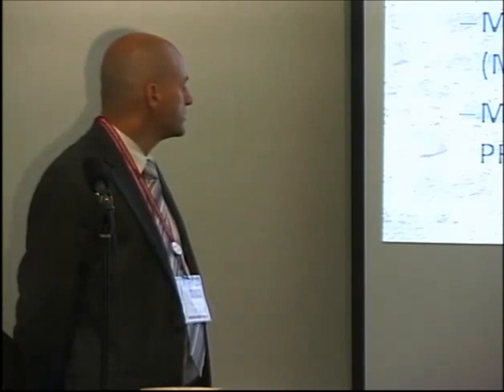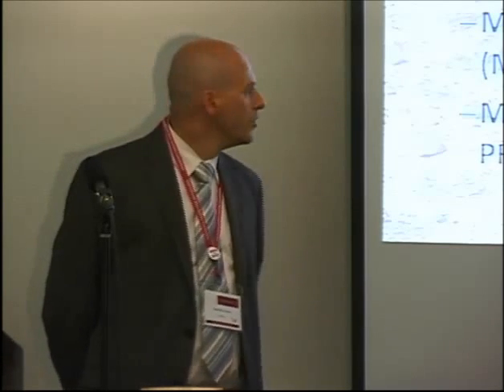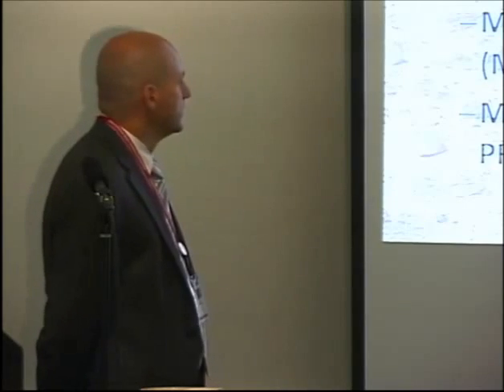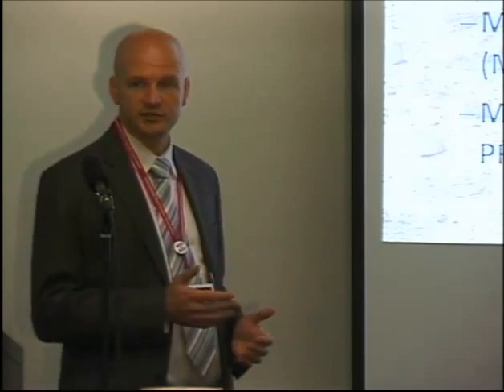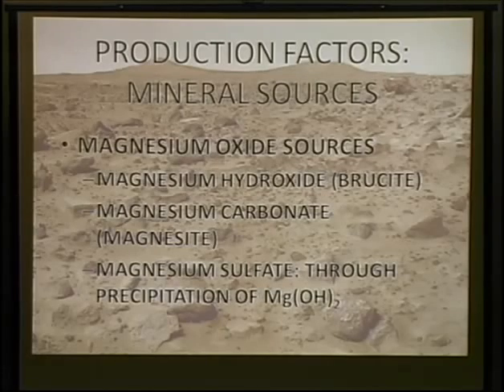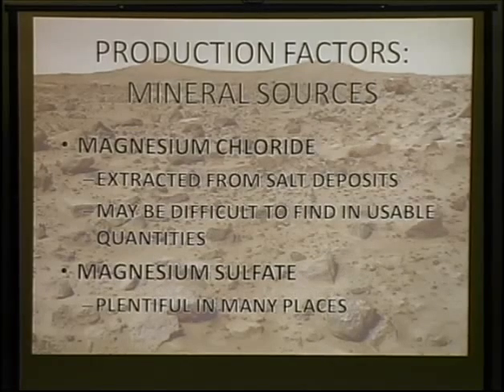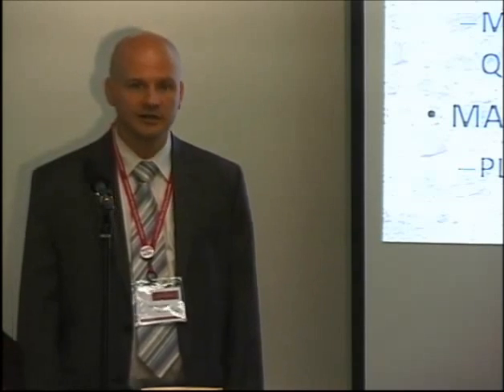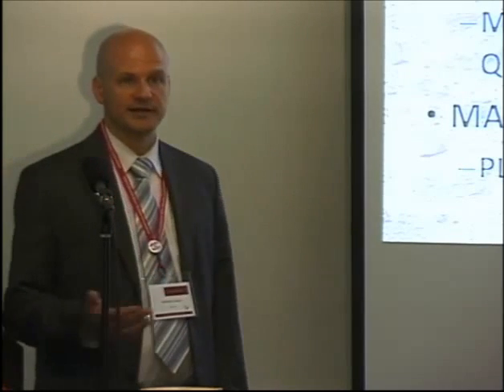And it can also be produced from magnesium sulfate, which has been found in large quantities on Mars. But it would either take a much greater energy input for direct decomposition, or it can be put into solution and we can precipitate magnesium hydroxide out of that solution to produce magnesium oxide with a much smaller energy input. Now, the magnesium chloride should be fairly easy to find in the salt deposits that have been found on Mars. Here on Earth, it's produced by separating it out of salt deposits or even seawater.